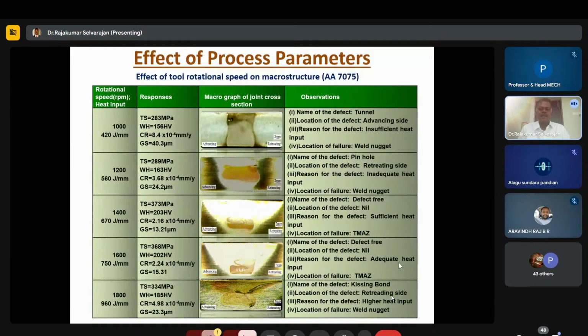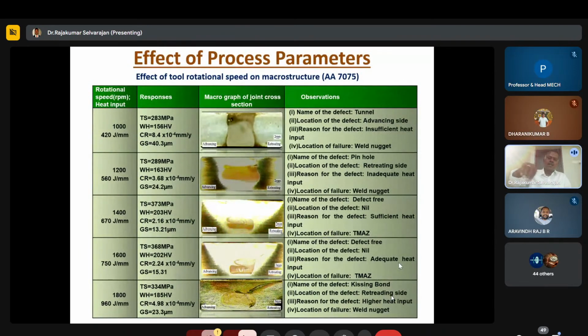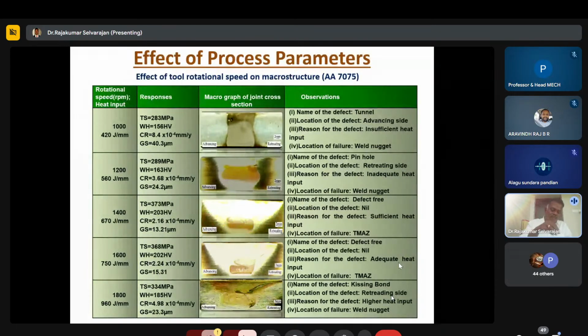Why does the defect occur on the advancing side? Normally when the tool rotates, the starting stage is the advancing side. Whatever material is pulled out from the advancing side will be stirred and redeposited to the advancing side. But because of the low heat input, the void is not fully filled, so it ends up with the tunnel defect. The location of the failure is the weld nugget. So we increase the speed in steps of 200 RPM.